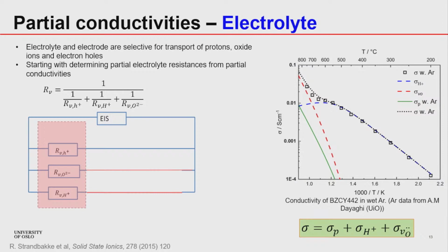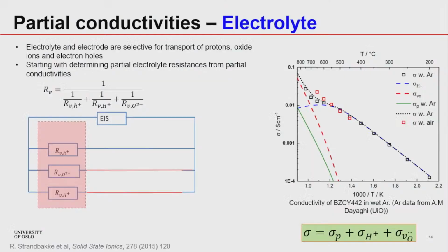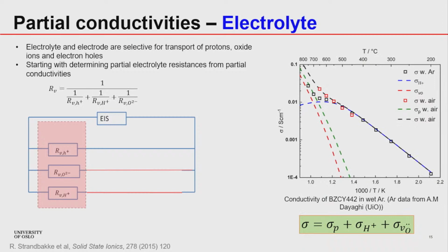Now, taking this as a base for the p-type conductivity, the difference in p-type conductivity between the wet air and the wet argon, we can fit the data and we can model the data to get more information. And here we see that the oxide ion conductivity and p-type conductivity has been modeled, and they are much higher than the wet argon atmosphere.